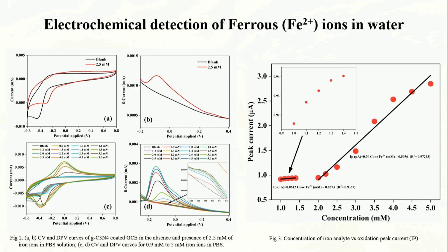So at that point, we are sensing ferrous ion, and we did a concentration study from 0.9 millimolar to 5 millimolar. We figured out that the oxidation peak forms two linear ranges with respect to the concentration. The first range we predict to be because of this hexagonal core shell structure, which absorbs iron at a really low concentration.